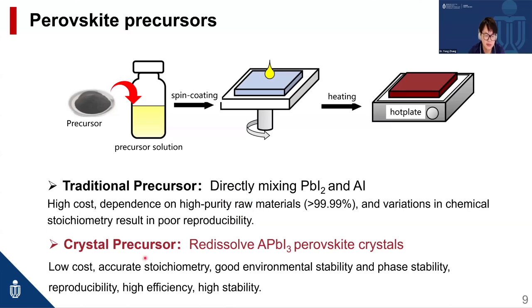Here we propose a method different from the traditional precursor: we use a crystal precursor by first synthesizing the FAPbI3 perovskite crystal, and then redissolving this crystal to fabricate the film.